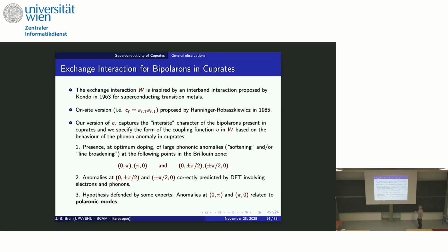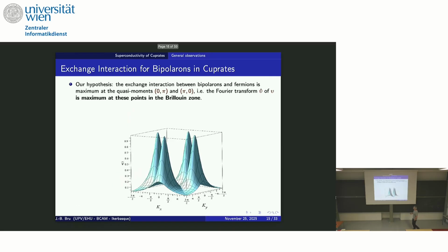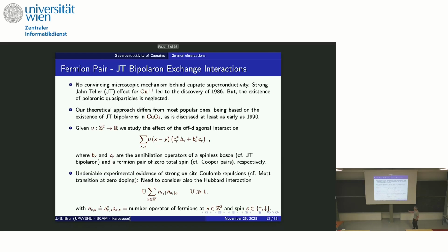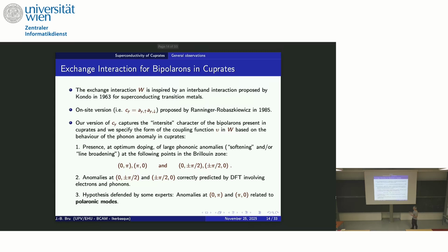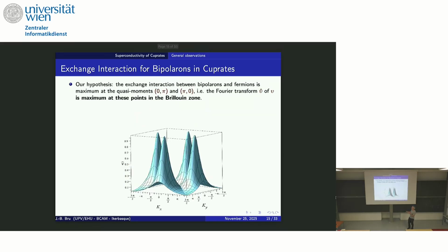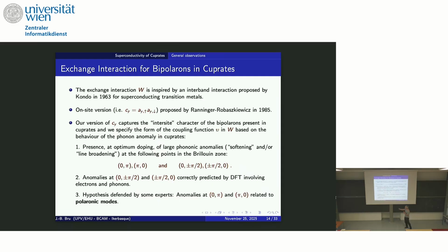And density functional theory, in which no creation of quasi-particles is taken into account, predicts this, but not this. One hypothesis is to say that in this particular case, what happens is a creation of bipolarons. That means that my function v here, if I take the Fourier transform of v, which is a function of quasi-momenta, should be maximum at this point. It should peak at this point. It's exactly what we did. We took this function v, the Fourier transform of v, peaked at this point, 0 pi or pi 0.